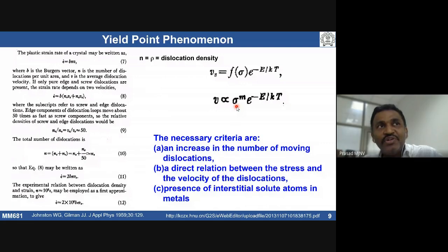Yeah, it depends on units. Unless you tell the units, you do not know. Typically it's 10^6 to 10^8 per meter square for annealed materials. In heavily deformed materials, when you deform the material, dislocation density can go to 10^12 to 10^14 per meter square. If I estimate how much carbon is required for these two materials, you'll get surprised.